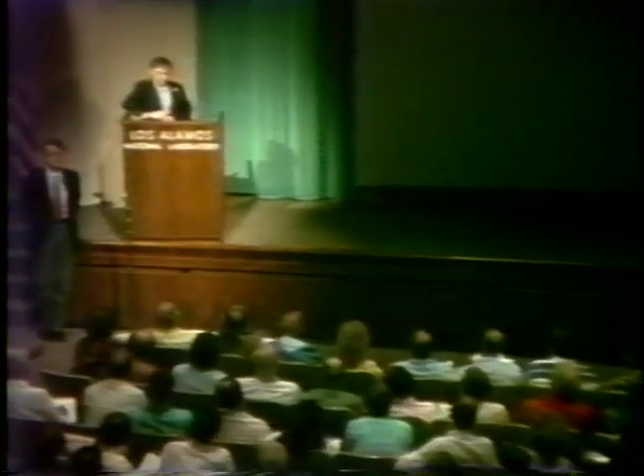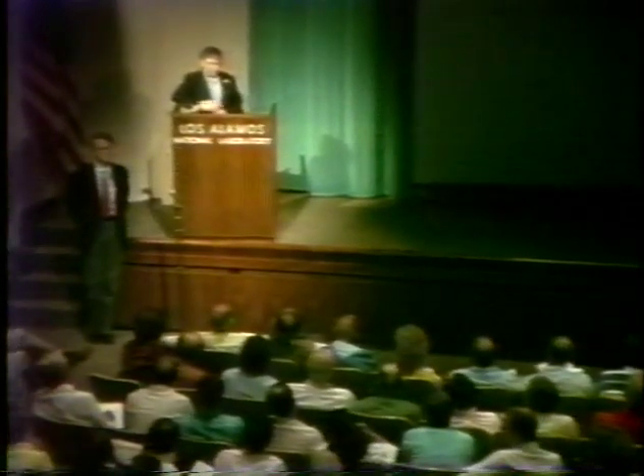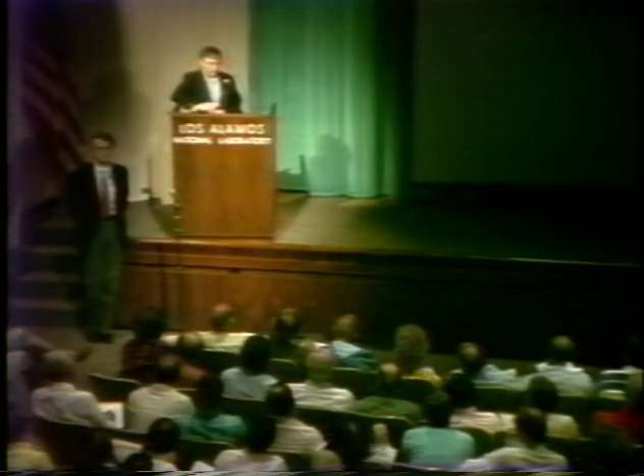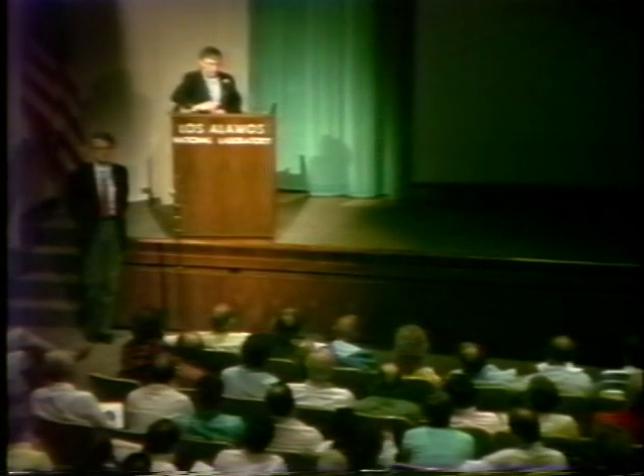Is there a short-term correlation between the current flow and the heat production rate? Short-term? Yeah, what's the time constant for changes in heat rate if you change the current? Well, the thermal relaxation time of the dewars we've been using is on the order of, I think, 1,800 seconds. So any change, you would have to wait that long before you could determine what the new cooling constant was. So the measurements are simply slow. Apparently it goes up, at least within that time frame, within hours.